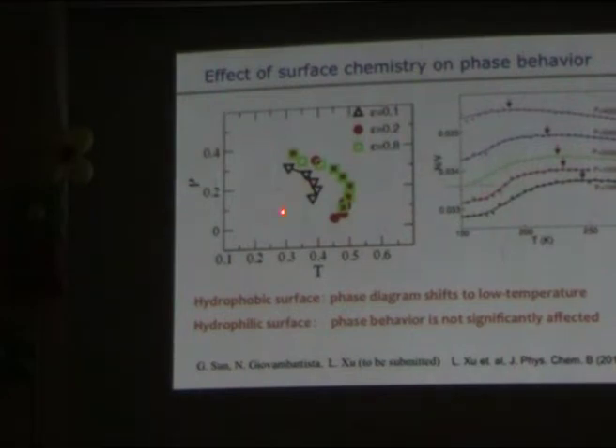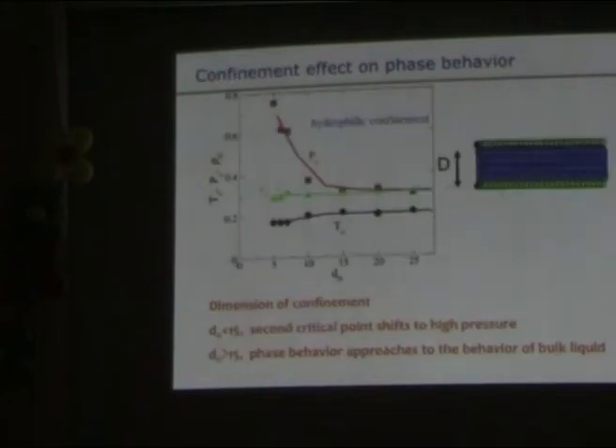First of all, the region shrinks, and secondly it is moved to the low temperature side. But for the intermediate, this is about contact angle 90, and this contact angle is roughly about 0. So this is extremely hydrophilic. You can see that for these two cases, the density anomaly doesn't change much. So this means hydrophilic. If the confinement surface is hydrophobic, then this is really dangerous.